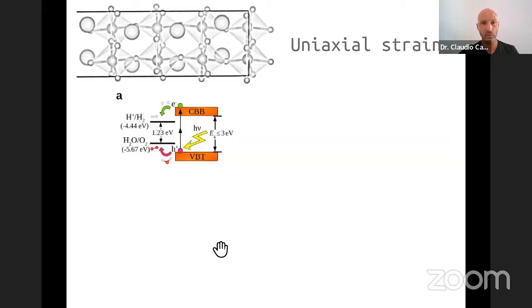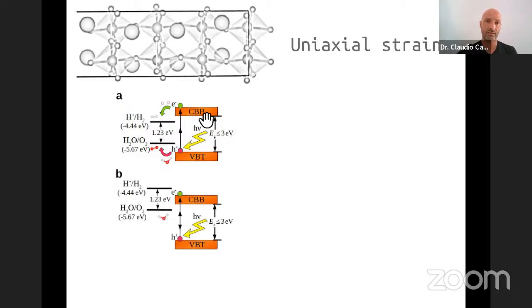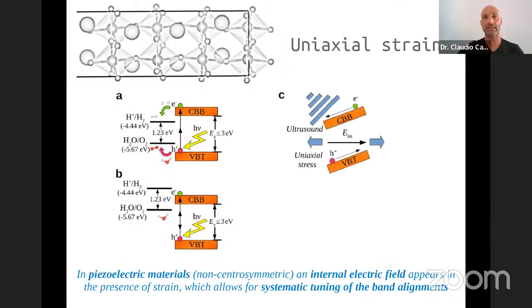Okay, so just as I said before, this is the ideal situation one wants for an ideal photocatalyst. So you want these two energy levels to straddle these reaction potential energies, right? So that you can introduce electrons and holes into the water molecule and form these hydrogen molecules, right? However, this is never the case, or most of the time you don't have this situation, but you have something like this, right? So even if your band gap is optimal for absorption purposes, in the sense that it's below 3 electron volts, right? Typically, the band alignments may not be good at straddling these two energy levels, right?